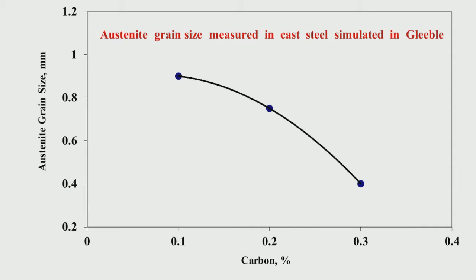Yeah, as I was telling you, we can measure the austenite grain size in the cast steel. Now, how is it done? We can simulate continuous casting in a machine we call a Gleeble, a simulator. So, what we can do is take a solid sample from different regions of a cast product having different chemistry, and then heat it till it goes to the liquid region, and then simulate the continuous casting by cooling it at a rate which is equivalent to the continuous casting cooling rate.